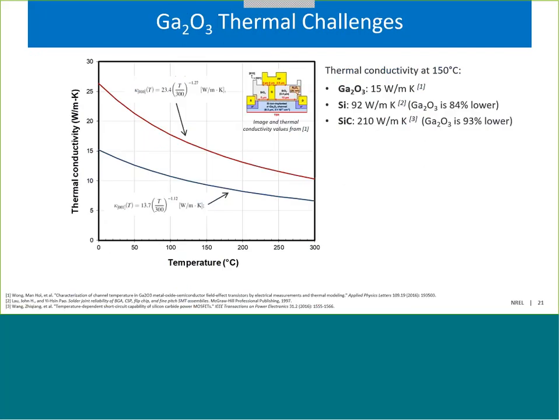This slide highlights one of the main disadvantages of gallium oxide, which is its low thermal conductivity. On the graph here, I am plotting the thermal conductivity versus the temperature. This data was taken from that first reference there from Wong et al. Gallium oxide has an anisotropic thermal conductivity. The thermal conductivity in the through-plane direction is shown by the red line, and that's about 40% higher than the thermal conductivity in the in-plane direction, which is shown by the blue line.